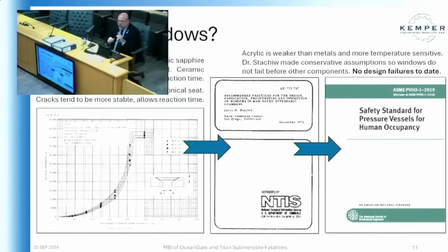And more importantly, the failure mode for these hard ceramics is often a crack that propagates in an unstable manner, so by the time you see a crack, it may already be fractured. Once it fractures, it loses the strength, and next thing you know, the inside becomes the outside, and when you're in a submarine, you really don't want to have a convertible. Whereas with acrylics, it is more likely to form a stable crack. First little cracks can be called crazing, and that is your warning to stop and reduce pressure. And of course, if you're in a submarine, reducing pressure means go up. But in a medical device, it would be back off your pressure. So do what it takes to stop yourself and then depressurize.